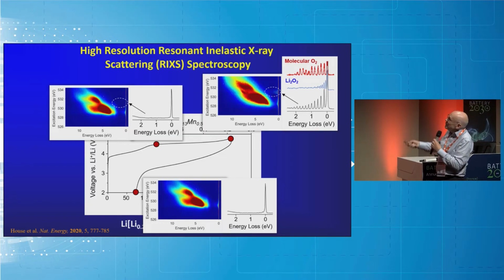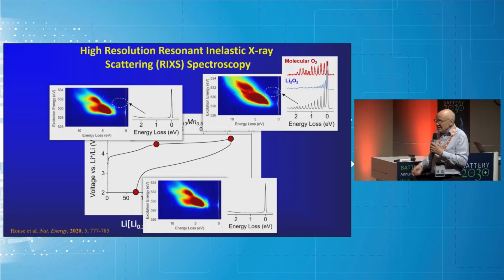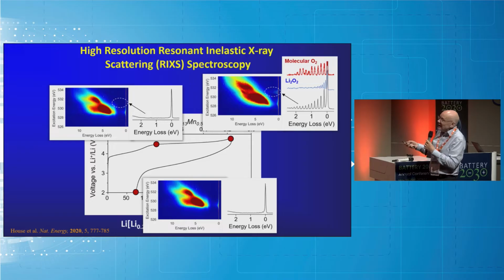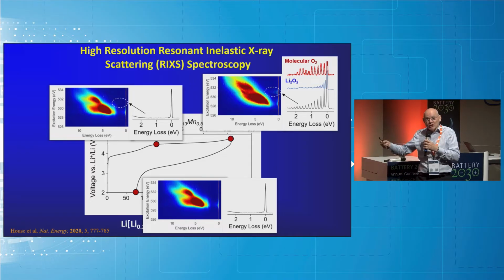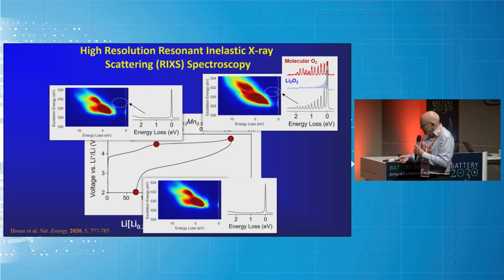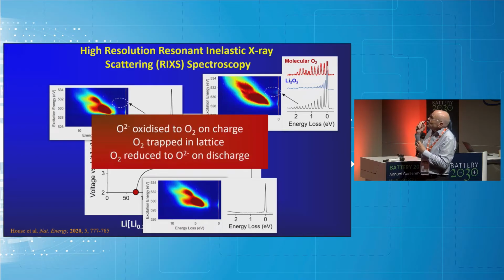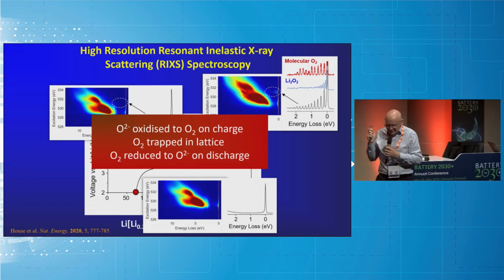So RIXS is powerful because, as I say, it's element specific. It's actually looking at the electronic states. These are cells, obviously, ex situ because it's high vacuum. You charge it up, you take it out of the cell, you put it into the spectrometer, and these are the results. So what we see is oxidizing oxide ions produces molecular oxygen, which is trapped in the particles.